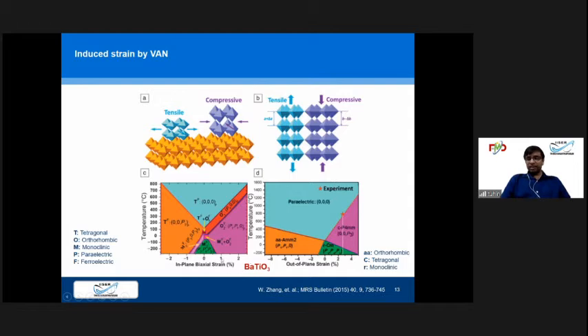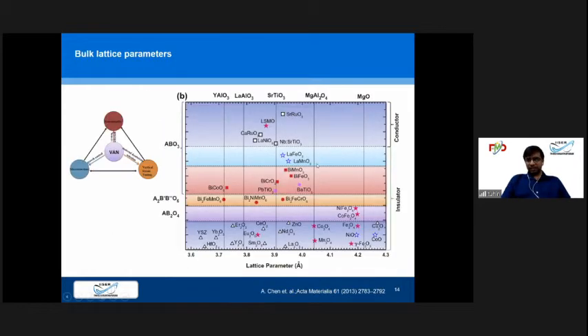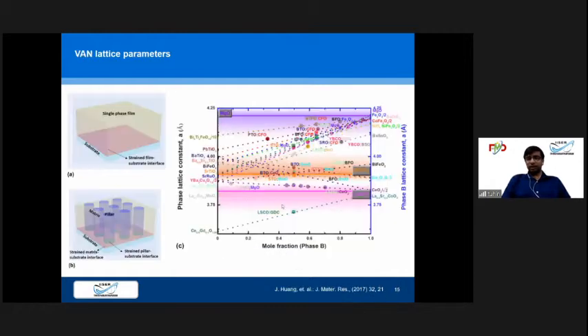So as you can see, by changing the strain and the deposition temperature, we can change the functional properties of these materials. So we'll go to one example here. As you can see, there are different multiferroic materials where the lattice parameter is very close to the substrate lattice parameter. Different ones of them are conductor, insulator, or metallic. So by just changing a little bit of strain, we can change their material properties. Like we can make an insulator metallic, and we can make a metallic material an insulator also. So this is a kind of phase diagram.